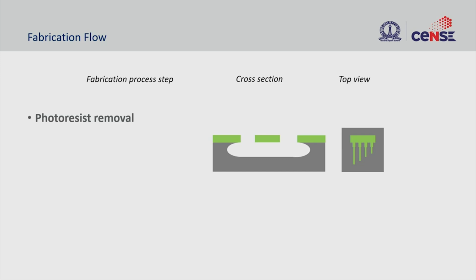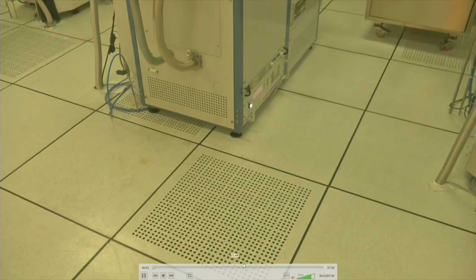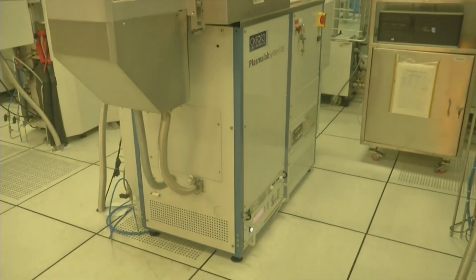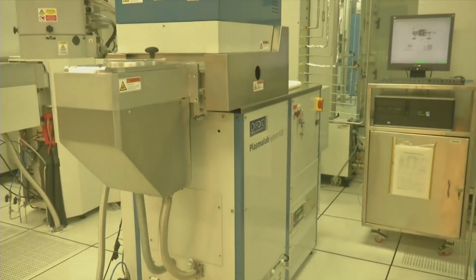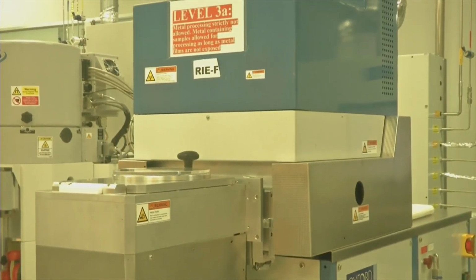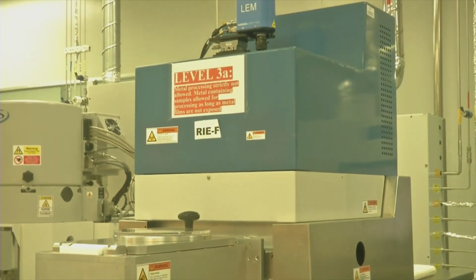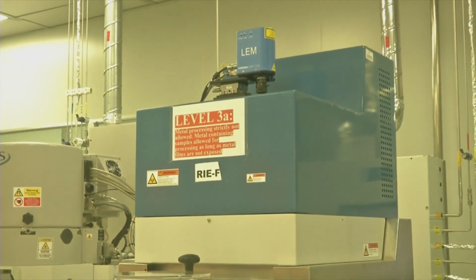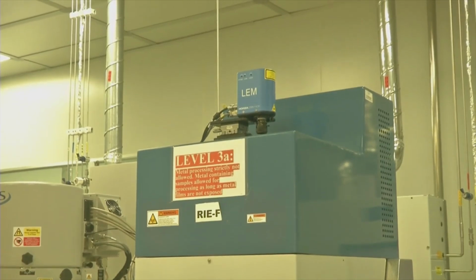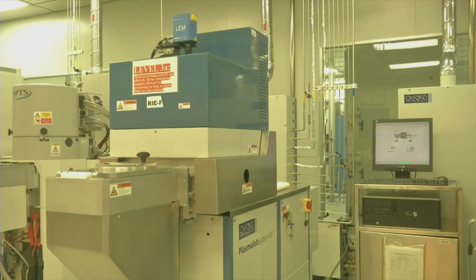On the whole, all three processes can be done using a single tool. In fact, we can sequence this so that all three processes are done in one go. That is what we are going to do in the next process. What we see here is an ICP RIE reactor, which we are going to use to etch silicon nitride anisotropically, etch silicon isotropically, and then remove the photoresist.